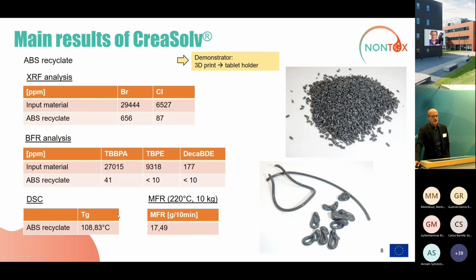Furthermore, if we look into some other data like the melting point, or the glass transition point, and the melt flow rate, we see typical values for ABS or recycled ABS. Here you see the color, which is probably a bit disappointing in terms of not being clear and white, but this is a typical color coming out of such recycling processes, and it is a color which can be reused and can be recolored at least into darker applications.